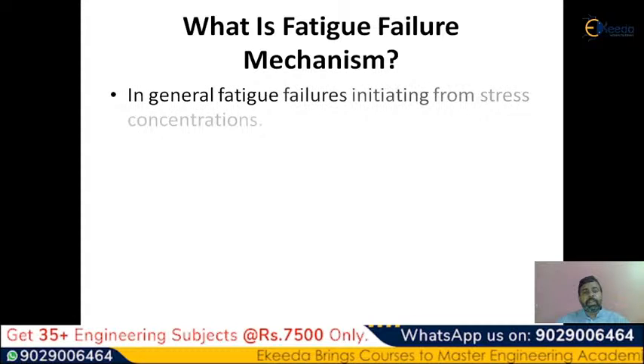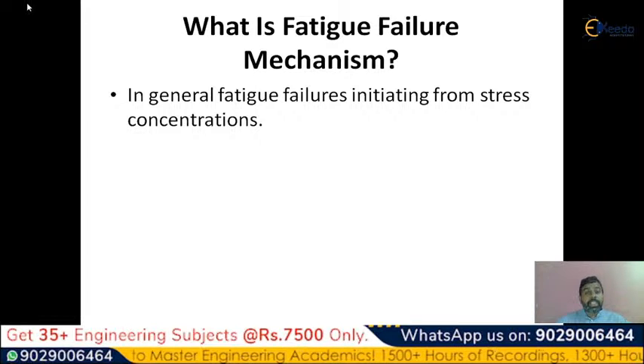Here, in general, whatever the fatigue failure that you are seeing, it is initiating from stress concentration. So that means what you have to observe is the stress concentration area, whatever stress concentration areas are observed in the material. So what can we do? See, we cannot avoid stress concentrations. We can reduce stress concentration. I repeat this particular sentence because this sentence is important to understand the fatigue failure mechanism.